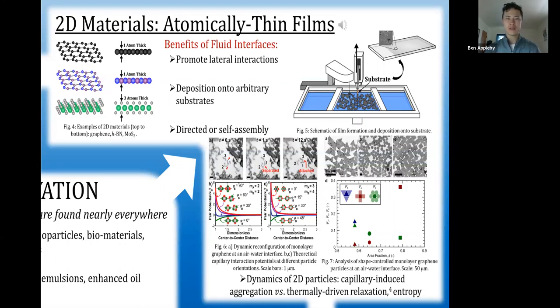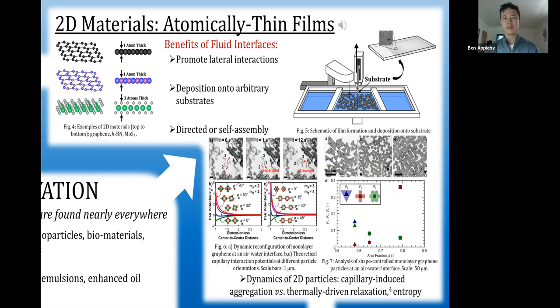In figures 6 and 7, some of the progress we have made in understanding the interactions and parameters that govern the structure of graphene particles filmed at an air-water interface is shown. Figure 6 shows a time-lapse of three graphene particles that undergo reversible attachment and detachment processes over a timescale of about 12 seconds. This is unique to 2D particles at a fluid interface, as most interactions between other types of particles such as spherical particles are strong and irreversible. We can begin to understand why these particles attach and detach by looking at the pair interaction potentials that govern the strength of attractions between two particles, shown in figures 6b and 6c.